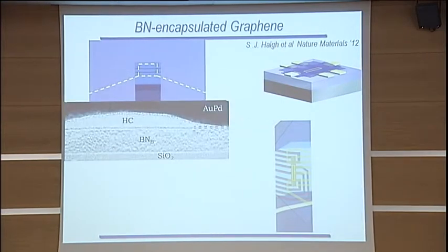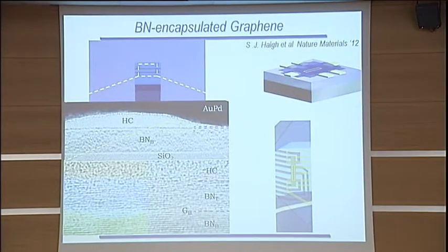we can take a look at it in the cross section, and that's our substrate silicon oxide, and the bottom boron nitride is over here, and then there is graphene, and then BN spacer, and then another layer of graphene there. And in principle, you can count all the layers, and with the EELS spectroscopy, you can even try to identify both of the graphenes there.